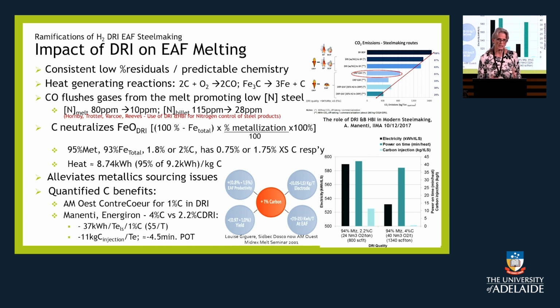The impact or importance of DRI in the EAF melting is basically consistency, lower residuals, and predictable chemistry going in. The heat generation from the reactions forming CO and from the reduction of Fe3C are also contributing to the system. And the CO is flushing the nitrogen, hydrogen from the steel. The carbon's neutralizing the FeO in the DRI also. And just an example, 95% met, 93% iron total at 1.8 or 2% carbon will have an excess of carbon in the actual DRI of 0.75 to 1.75.